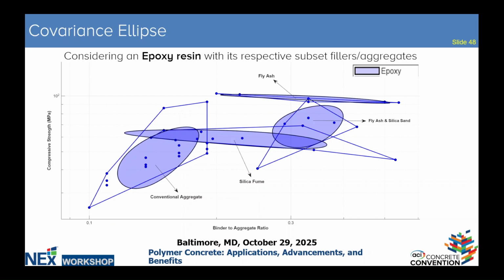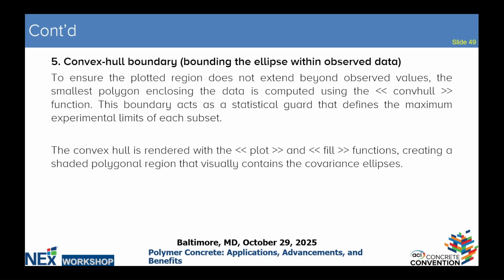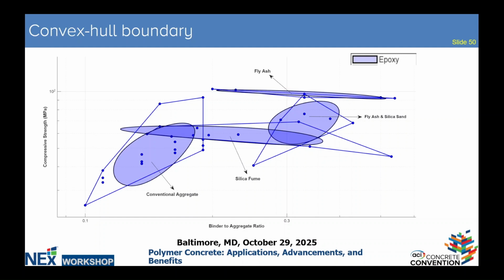And as I initially said, you have to enhance the subset data, which is the mother ellipse, which is the epoxy, where we are yet to enclose the whole subset data into one union. So we have the convex boundary, which is bounding the ellipse, to see that there is no data being extrapolated aside the boundary. We're trying to draw a polygon around the data set to see that it fits within the boundary, which is the convex hull. So we have the previous data here, and we just fit it with a polygon. You can see everything is enclosed in this polygon here, and we finally draw our final ellipse.